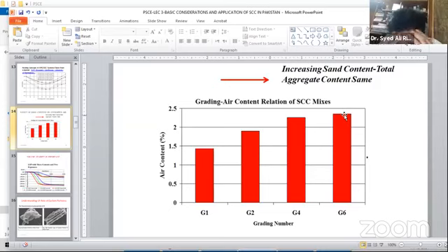because in freezing areas, if you want to make concrete, you want to have more air content, so use more sand. I mean, G6 with 55% sand and 45% coarse aggregate will be ideal. It will require less air entraining agent, and then you will be making an economical concrete which is resistant towards freeze-thaw problems. And many other conclusions can be drawn from this picture. This also appeared in some of my papers. If you want to have any questions, please get it recorded.